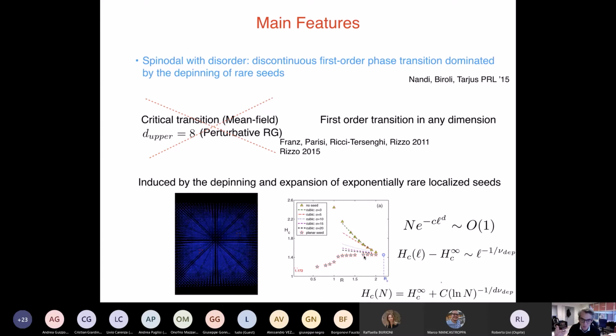And then what's going to happen in a real system is that in a very large system of size n, well, the probability to have a seed of the other system is small. It goes in general like exponential minus c L to the d, where L is the linear size of the seed. And so, if you want to have at least one seed of size L, this must be of order 1. So this gives you the largest seed that you can have in a system of size n.